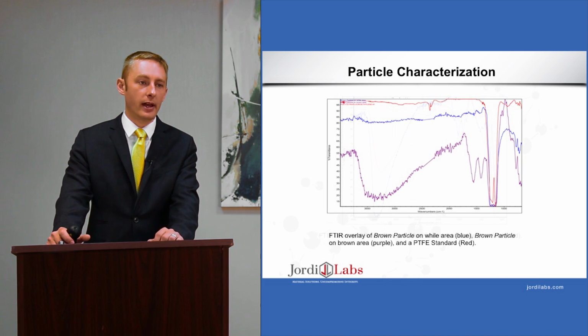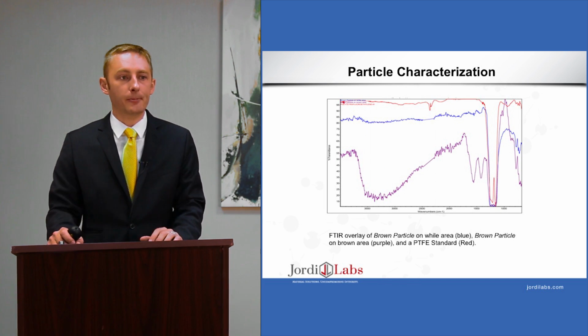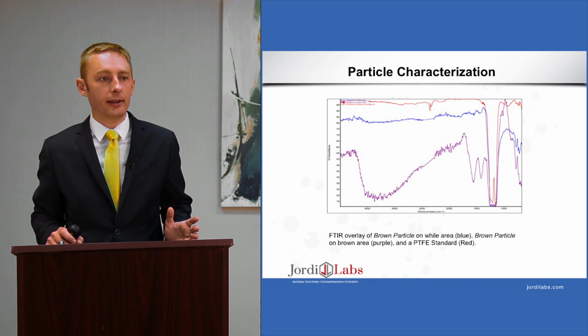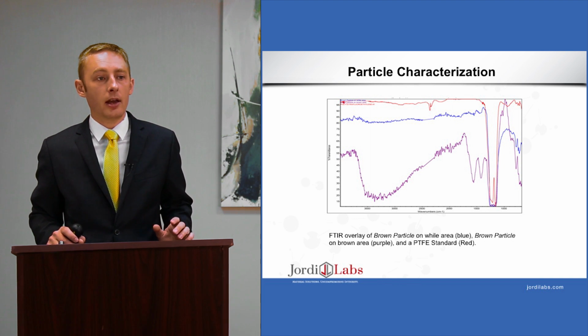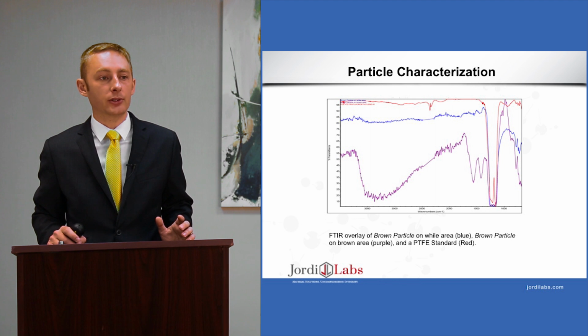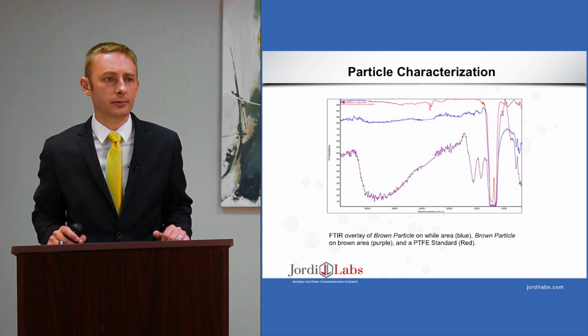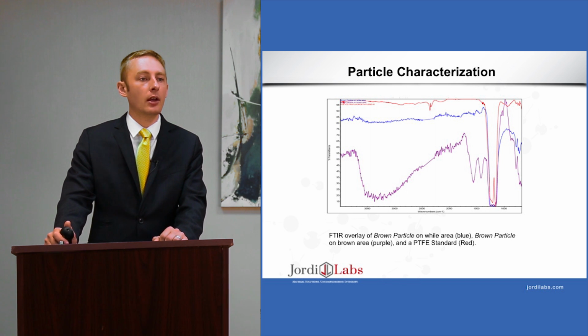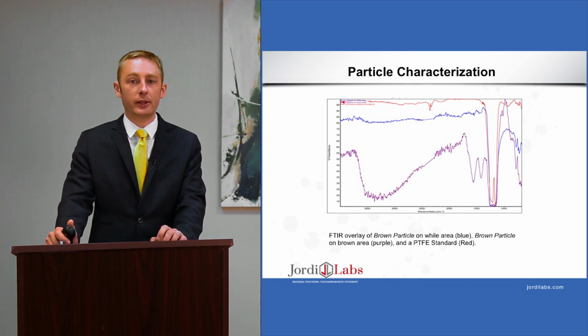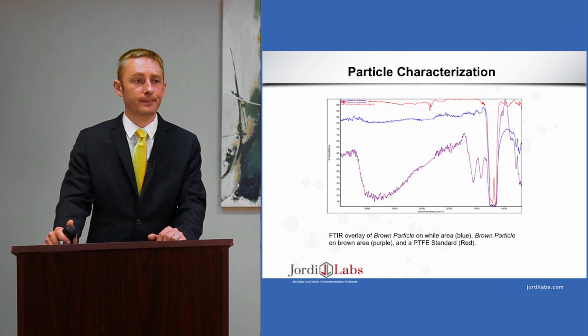And in this case, we have our brown particle. Our brown particle overlay with a PTFE standard, and we also have, I believe, a separate area on the particle. They overlay quite nicely, and we can see some good signals to confirm this for us.